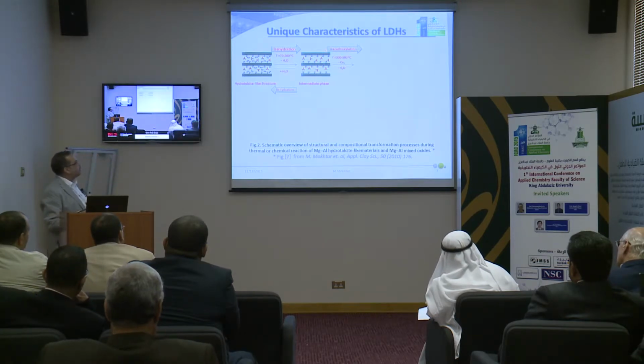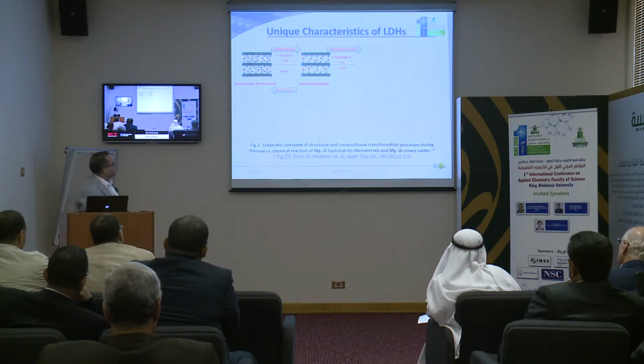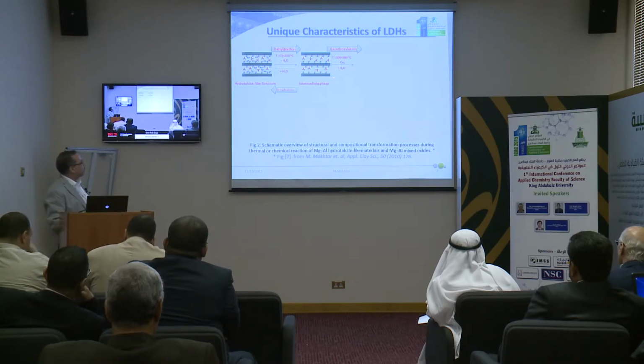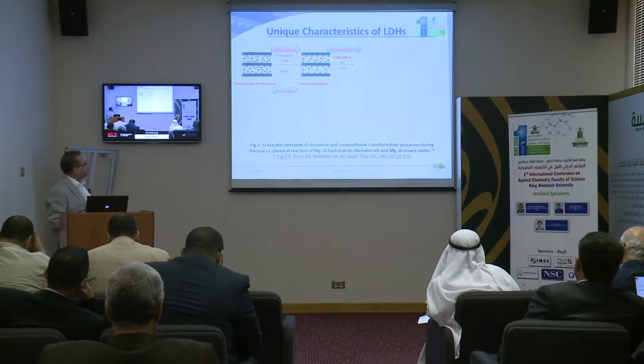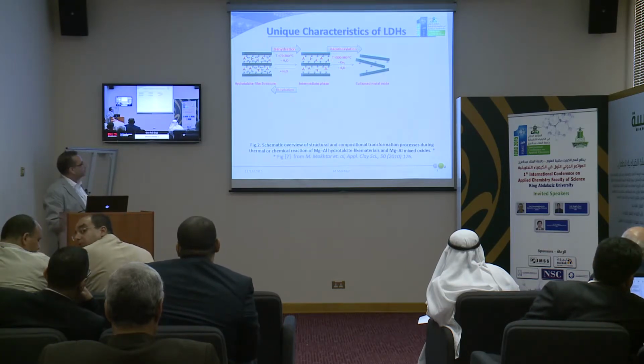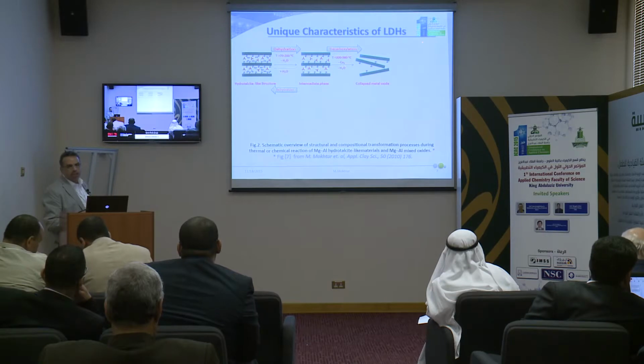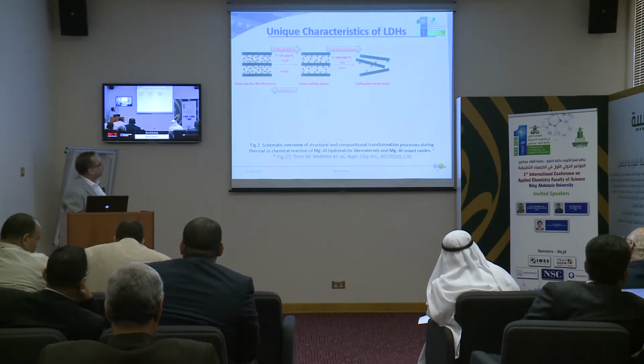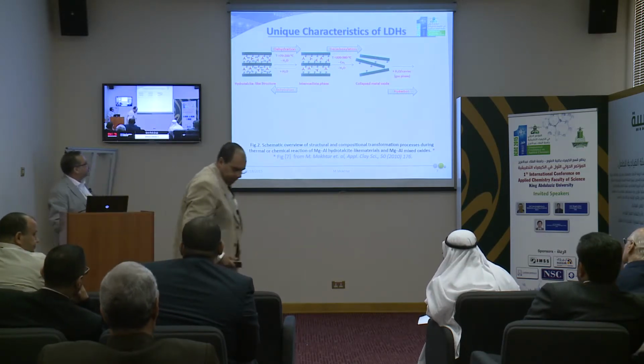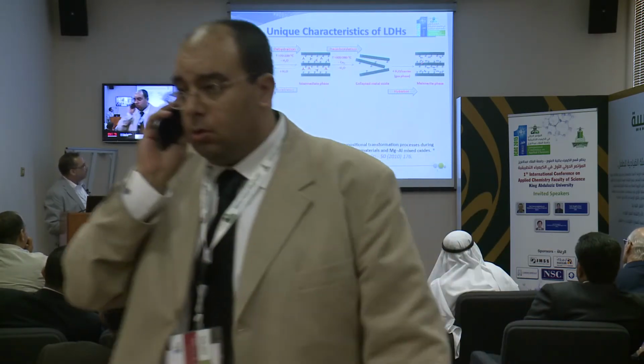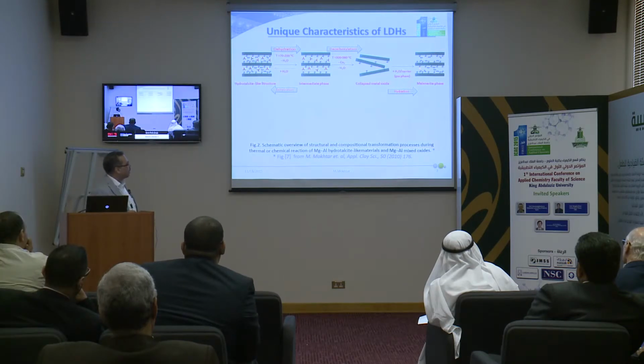If we decarboxylate the material by increasing the temperature from 300 to 580 degrees centigrade, we could completely remove the carbon dioxide and water molecules from the interlayer, so we have the collapse of the structure. A mixed metal oxide is formed in that case, and if we hydrate the material again, we'll never have the original structure, but another new material which is called meixnerite, where the hydroxyl ions are only substituted in the layers, while the carbon dioxide is completely removed.